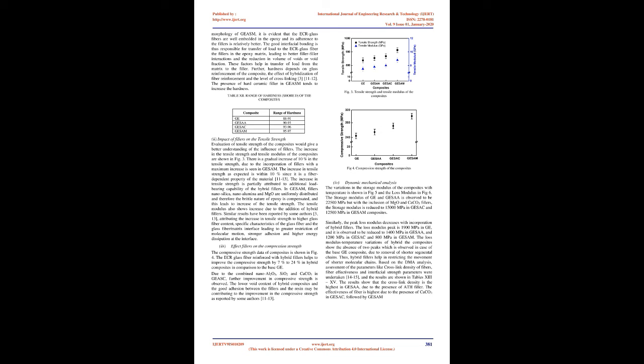D. Effect of fillers on the dielectric strength. The results of the 50 Hz AC electric strength of the composites across 3 mm thick samples, which were evaluated for the flat-wise, across the thickness, and edge-wise electric strength, across the surface, are shown in Table 7. There is a gradual increase in the AC dielectric strength across the thickness of the composites due to the incorporation of nanofillers and their combination with microfillers. The edgewise electric strength did not show differences due to the addition of nano and microfillers.